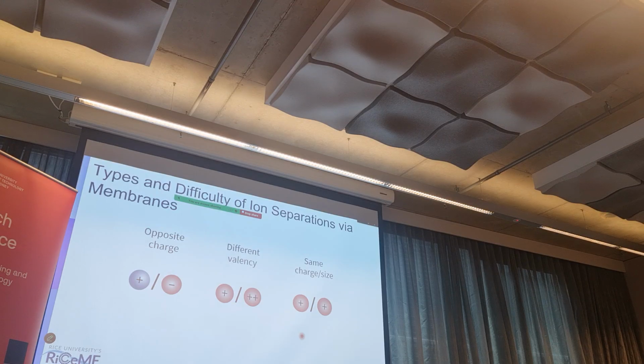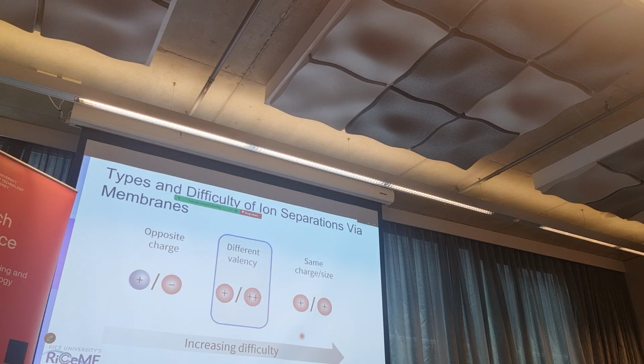And the most challenging are the ones with the same size and charge, like sodium and lithium, magnesium, and let's say copper and cobalt, and so on. These are difficult because they are quite identical, and you need a more sophisticated way to recover them.